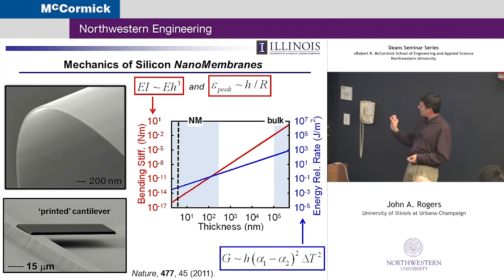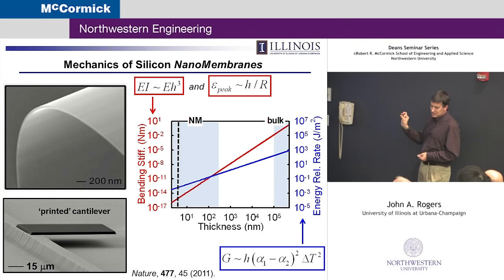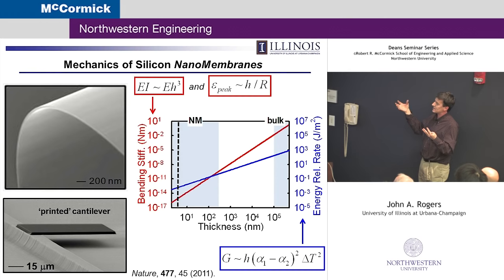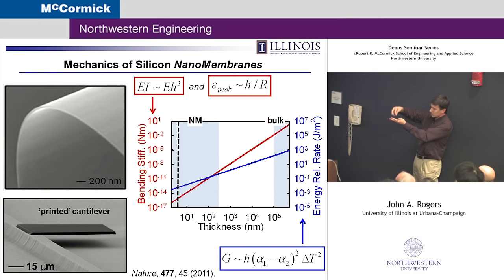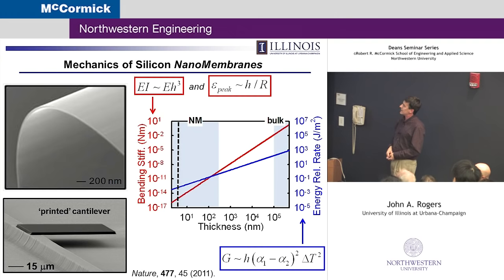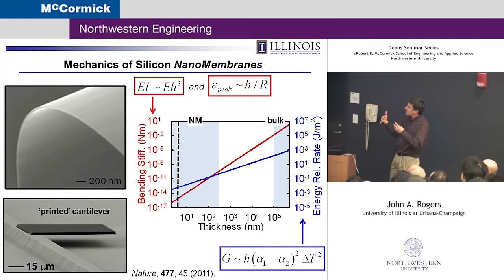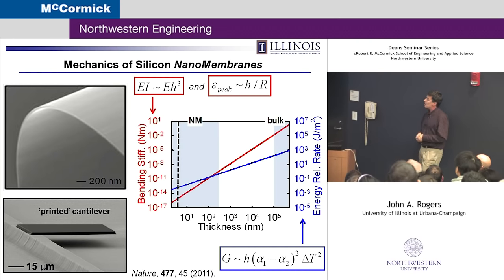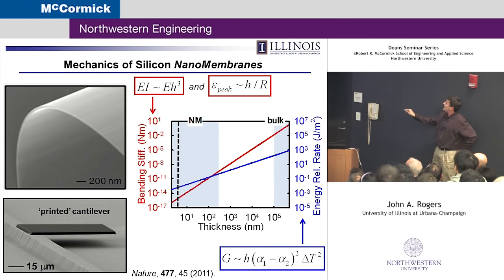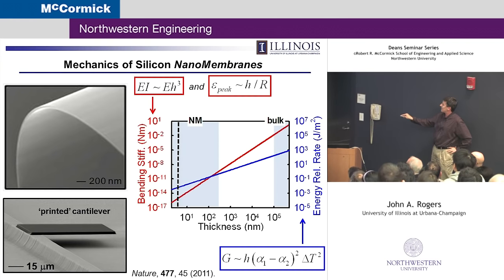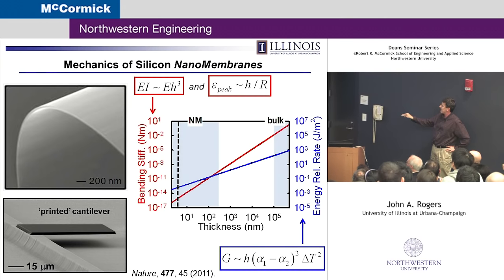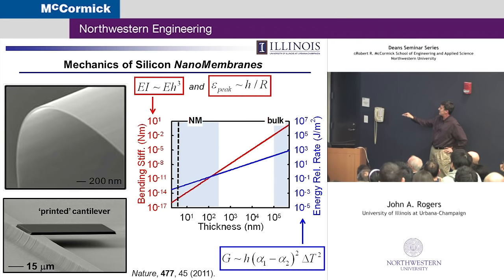And if you think about the challenges of doing that at a wafer scale, extremely daunting because you have huge differences in thermal expansion coefficients of silicone rubber and silicon wafer. So it's very difficult to take a wafer and glue it to a piece of rubber and make a realistic technology in that way because the mechanics are such that the interface stresses are enormous due to temperature changes. In fact, the energy release rate, which defines the propensity for a crack to form in a heterogeneous integrated system like that, scales with the square of the difference in the coefficients of thermal expansion times the square in the change of temperature. But this is an interesting scaling. It's linear in the thickness.